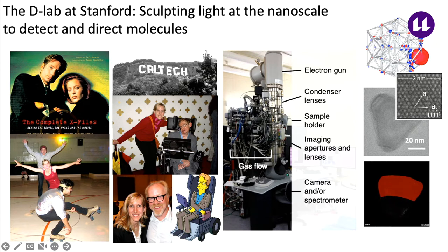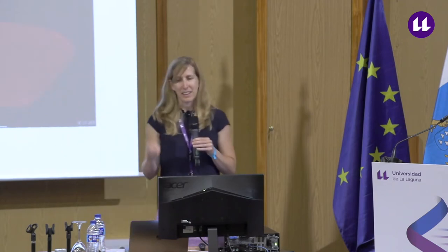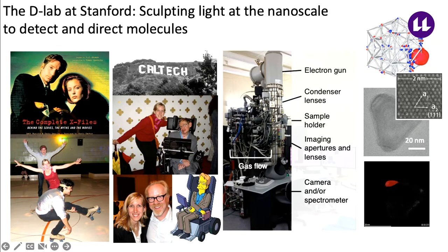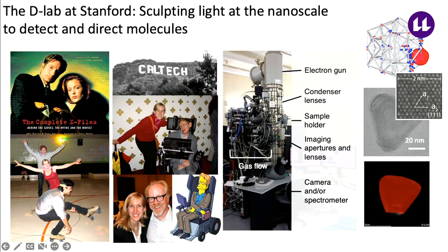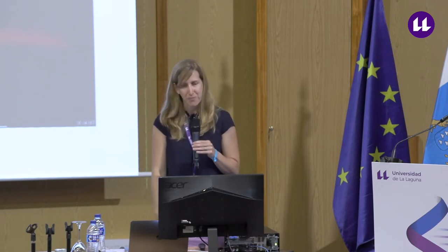In the movie shown here, you can see hydrogen splitting and then intercalating into a palladium nanoparticle. With atomic-scale resolution, especially in bimetallic nanoparticles, we can figure out which atom is where, and then link what we see in the TEM to first-principles calculations of excited-state properties. You can see a full atomistic simulation of the excited state of a palladium-silver nanoparticle — right where the silver is, there's a higher concentration of electron density. But today is really focused on detection of molecules rather than directing them in photocatalysis.